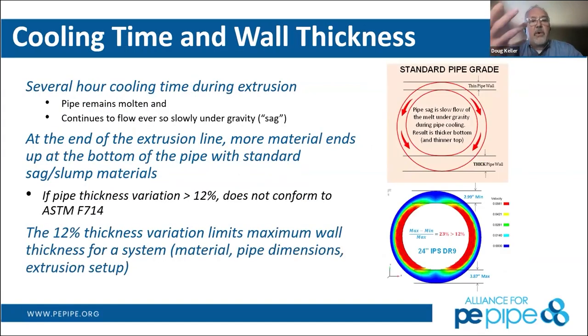So because of that several hour cooling time, what happens is you still have molten polyethylene in the middle of the pipe wall, and gravity is still pulling on that material, and it causes material to move from the top of the pipe to the bottom of the pipe, which means that the top of our pipe gets thinner, the bottom of our pipe gets fatter, and that's not what we want.